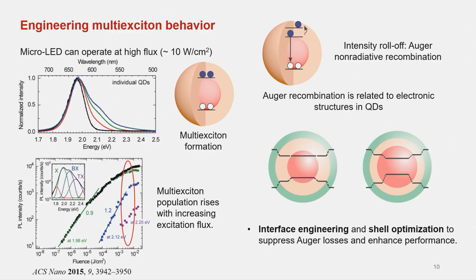Overall, all these multi-exciton behaviors are highly related to the electronic structure, which eventually comes down to how you build these core-shell structures: the thickness, the core size, and the shell composition. So we're going to have a more detailed understanding, using interface engineering and shell engineering to understand and optimize. Basically, the idea is to optimize the quantum yield, but at the same time minimize the Auger recombination rate.